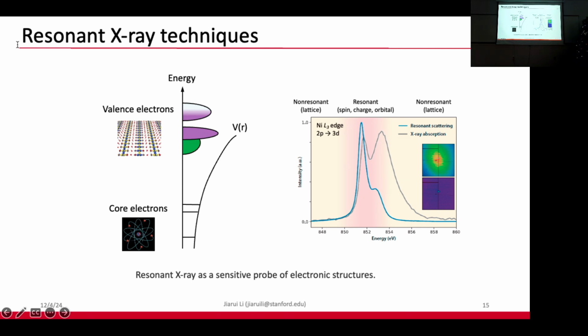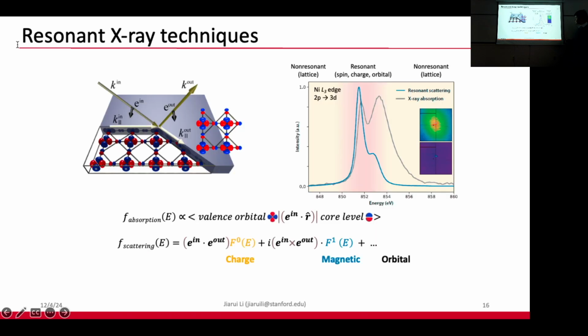So this shows that with this resonance effect, you do get a very strong enhancement in the signal, or the sensitivity that you can have for probing the valence electrons. And the theory calculations show that this enhancement can be more than a factor of 1,000. It is a huge enhancement.